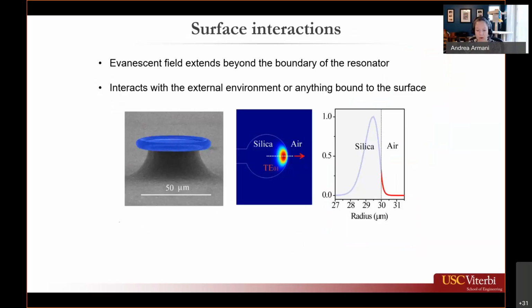One of the reasons why whispering gallery mode devices are a very interesting platform to combine with a surface coating is because that circulating optical field isn't confined entirely inside the cavity. So a little bit of it leaks into the environment, and this is called the evanescent tail. So anything you put on the surface will directly interact with that circulating optical field, and because the optical field is very intense, it will have a very strong interaction.